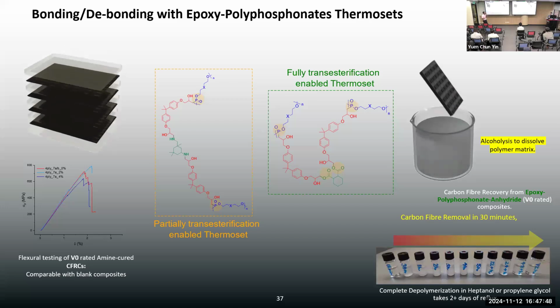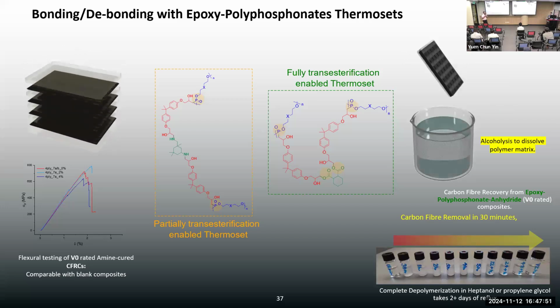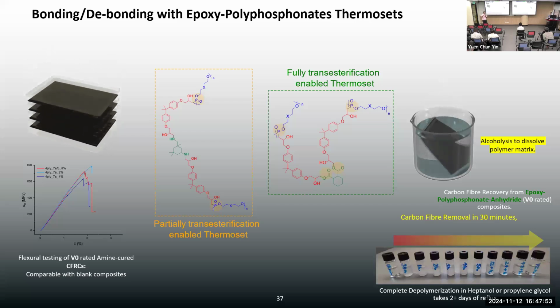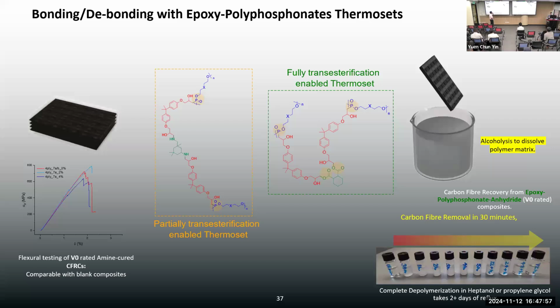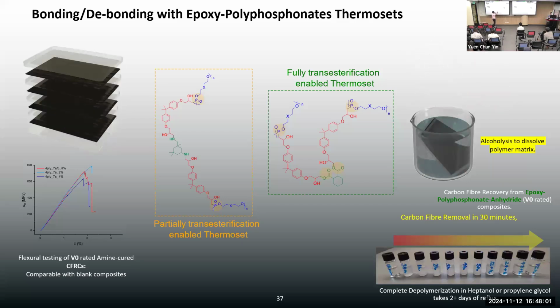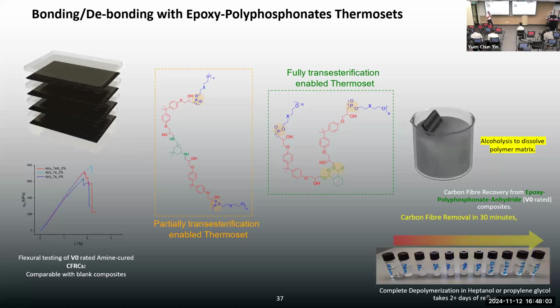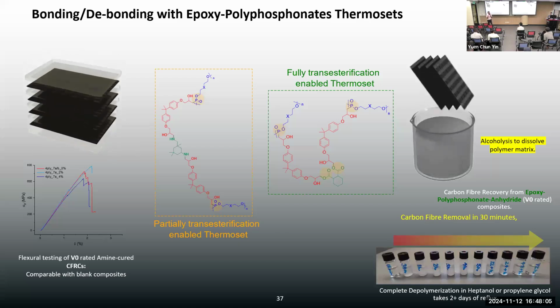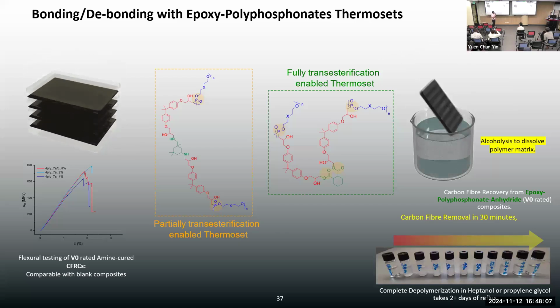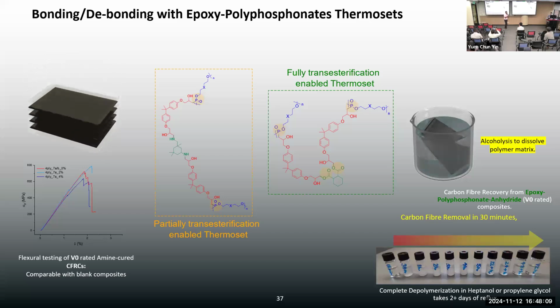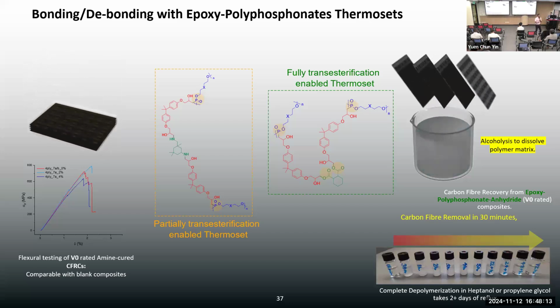And the way we do it is by removing the polymer, which is in between this fabric, by an alcoholysis process. So in our system, we put the composite in an alcohol, heat it up, and it opens the structure, okay? And when it opens the structure, you can separate the fibers and recover the fibers. This is called chemical recycling.